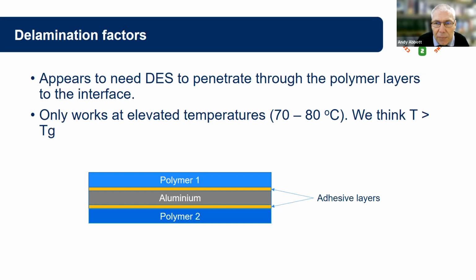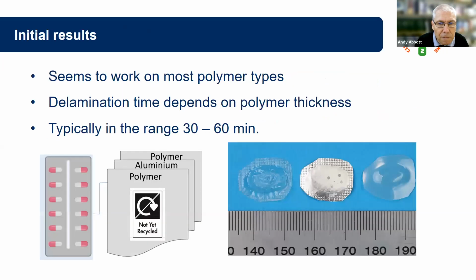We found that typically about 70 to 80 degrees is the temperature our processes need to work at. The concept is that we take our blister packaging and get the solvent to go at the interface. The time taken to delaminate these layers depends very much upon the type of polymer, in terms of its structure and particularly its density, and on the thickness of the polymer as well. We have found that almost all polymer multi-layers can be split in this way.